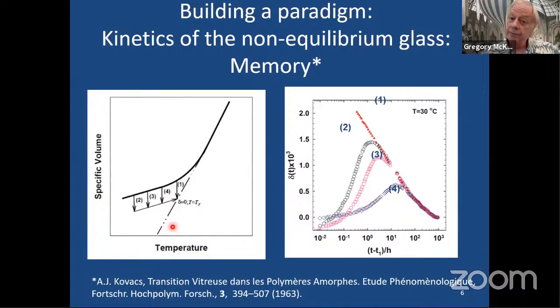The third experiment that was carried out by Kovacs in his signature, though, was the so-called memory effect. And in this, it's a two-step history instead of single steps in different conditions. So what he did was he first would bring the sample down to this temperature. You always start at T0 and jump down and let it age. So this would be the classic aging experiment.